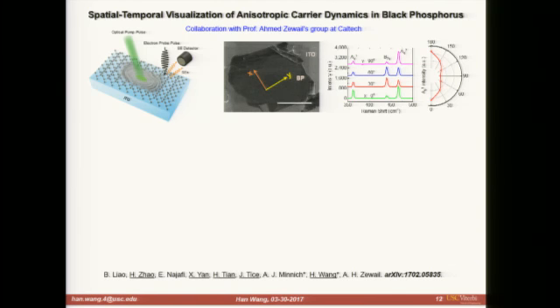Basically, the system they built integrates an ultrafast laser with an SEM. They have an ultrafast laser source that is split into two: one is the pump laser, and the other goes through a few frequency multiplication stages to ramp up the photon energy, and is used to excite the filament source in the SEM that generates the electron beam. The result is a time-correlated system with time resolution down to hundreds of femtoseconds.